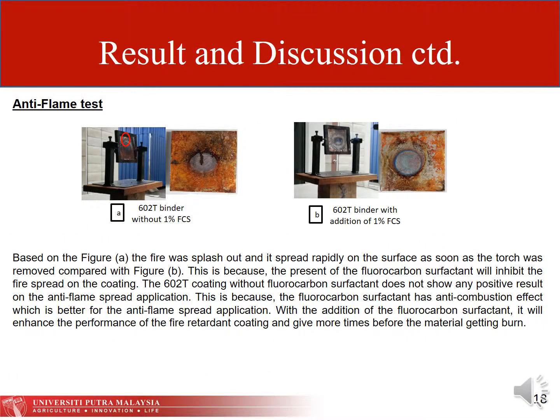In the anti-flame test, based on figure A, the fire splashed out and spread rapidly on the surface as soon as the torch was removed, compared with figure B. This is because the presence of fluorocarbon surfactant will inhibit the fire spread on the coating. The 602T coating without fluorocarbon surfactant does not show any positive result on the anti-flame spread application. This is because the fluorocarbon surfactant has an anti-combustion effect, which is better for the anti-flame spread application. With the addition of fluorocarbon surfactant, it will enhance the performance of the fire retardant coating and give more time before the material gets burned.